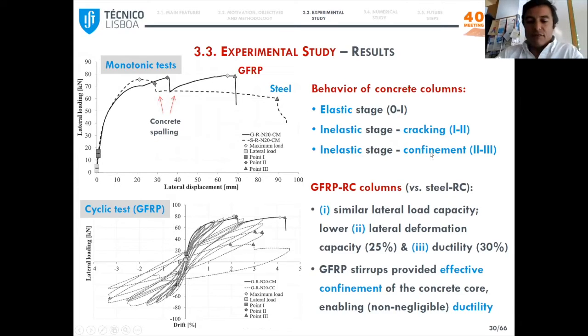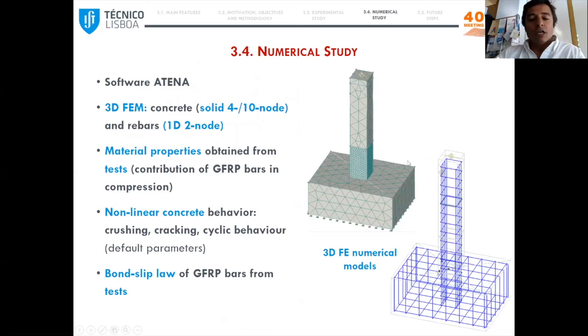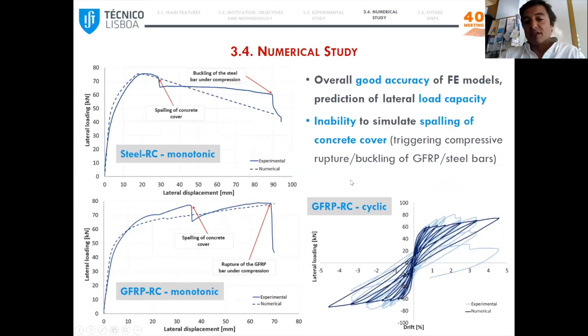this lateral deformation capacity. So for the numerical study, we used the software ATENA, to develop 3D finite element models of the columns. Material properties were obtained from tests, as well as the bond slip law used for the GFRP bars. And at this stage, for concrete nonlinear behavior, we considered the default parameters from the FE code. So we need still to do some additional research in this topic. So here you can see the results obtained in these preliminary simulations.